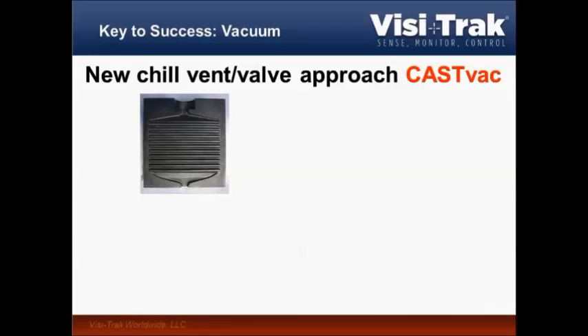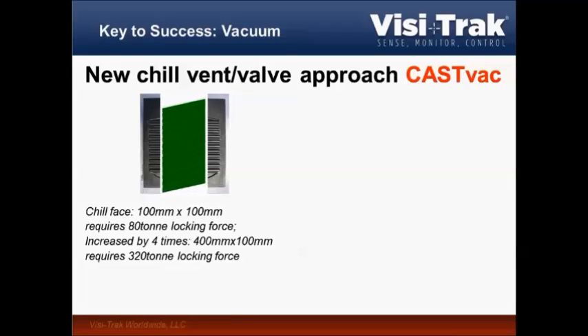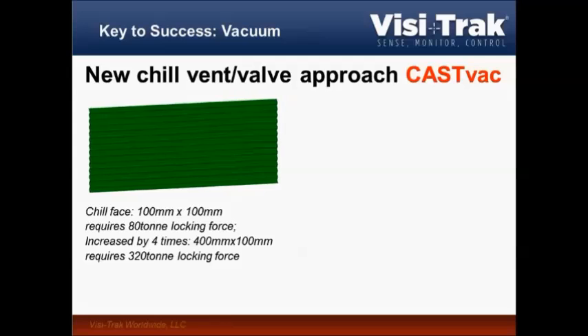Now, a lot of people say, well, why can't I use my traditional chill vent approach? Well, I guess you could. If you look at the CASTvac system from Australia, that is a very interesting approach because, of course, a simple chill vent would be way too small to evacuate enough, but if you increase that area by, let's say, 4 times, so your 80-ton locking force that you require for your chill plate would now actually become a 320-ton locking force. So if you actually need 2 or 3 or 4 of those to evacuate a big die, you can imagine you would need a bloody big machine now.